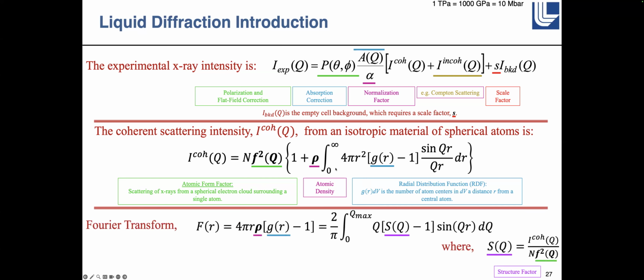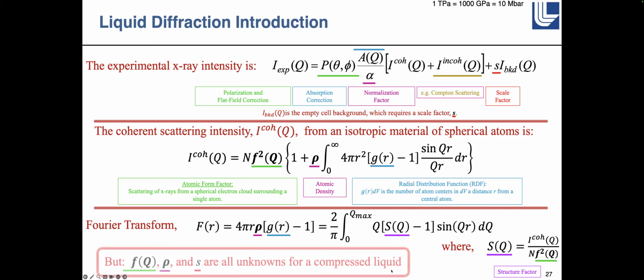So you can Fourier transform this coherent scattering, and you can write it in terms of the coherent scattering divided by the form factor forms the structure factor. You can Fourier transform the structure factor to get the radial distribution function, and that's kind of the standard way that people analyze liquid data.